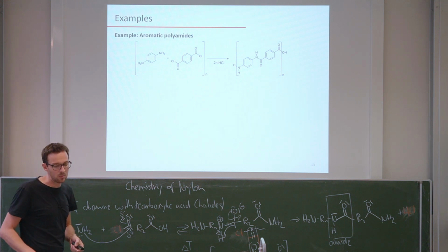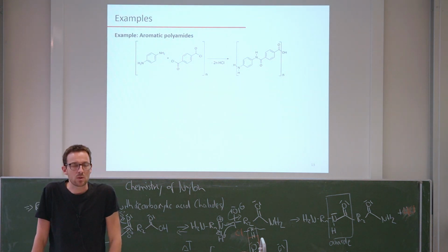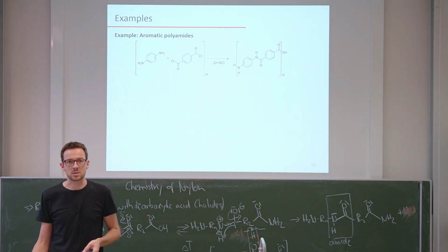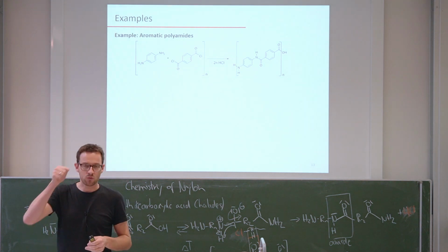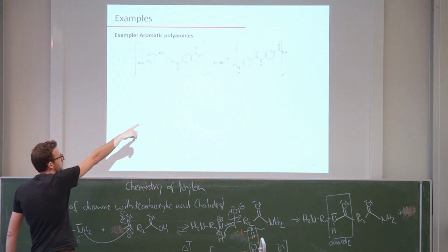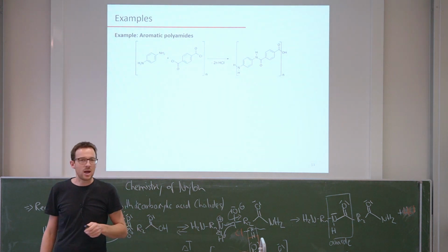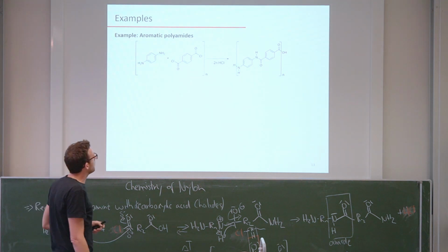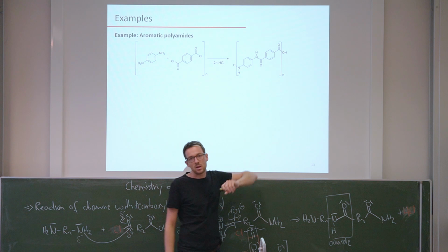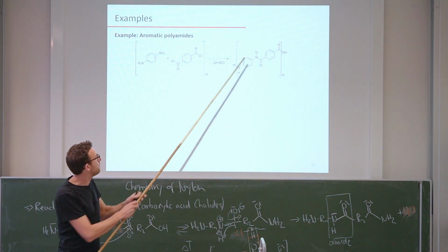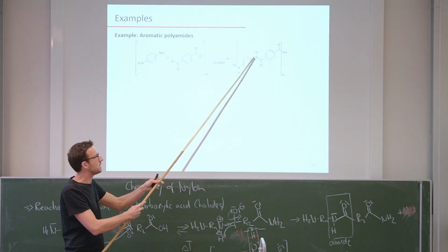Okay, so here's an example of something that is very sturdy. This material is known as Kevlar, and this is, for example, what is used in bulletproof vests, in fire-resistant materials, what the firefighters wear. When you have torches, the material that soaks up the oil to light the torch is also made from Kevlar. So you react an aromatic amine with an aromatic diacid halide and then create a nylon type material or a polyamide that is only composed of benzene rings and amide bonds. These can undergo hydrogen bonding, and these are very rigid and stiff materials.